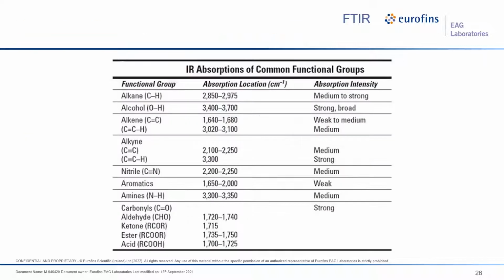And of course, you can also do it the old-school way: use the absorption bands corresponding to their functional groups to figure out the basic functional group, and based on shifting, you can solve a puzzle, basically. For example, if you see something around 1700 to 1800, that's most of the time a carbonyl group. And the different shiftings can be related to what kind of functional groups the carbonyl is attached to.